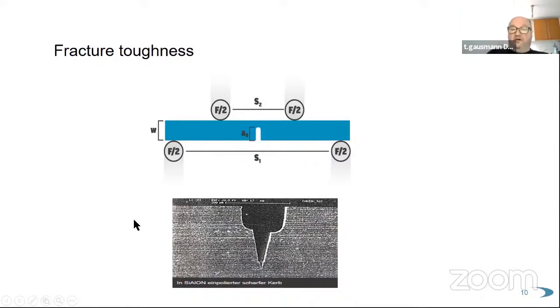In the norm for the fracture toughness test, it is required that your cutting edge, here is a microscopic picture, but not from dental ceramics, has to cut at least one grain into two halves. So one ceramic grain must be cut into two halves with an edge. The point is, there is no edge on earth that can do this cut, because the ceramic grain is so fine, you have no knife, no edge, nothing at all, that can cut half a grain of zirconium. When you can't do anything in testing according to the norm, forget about the testing results. They're not valid because they're not reproducible. So that is a big problem with this.